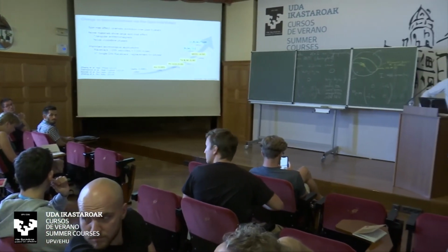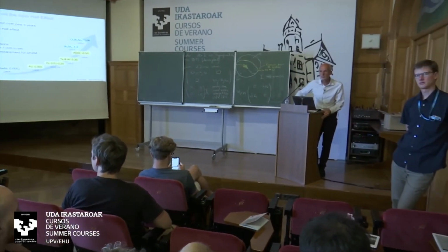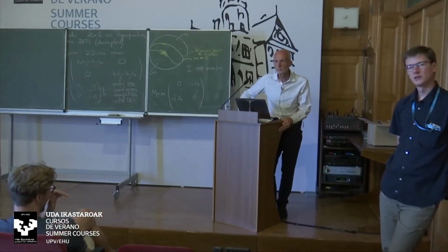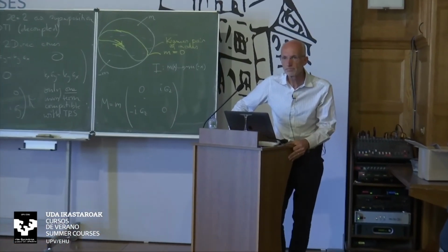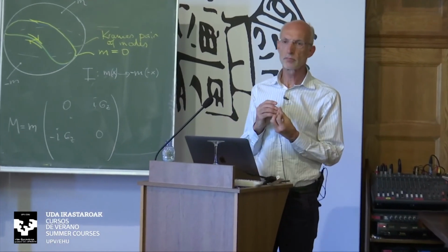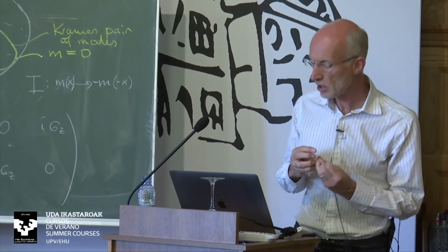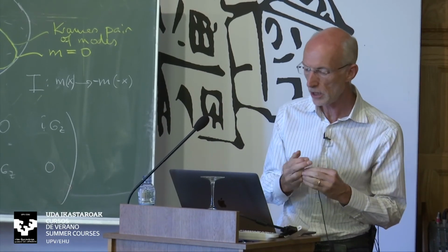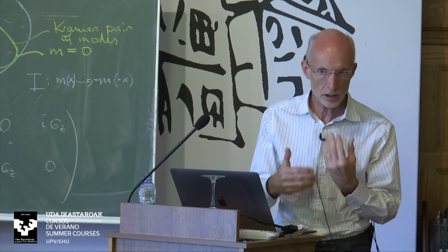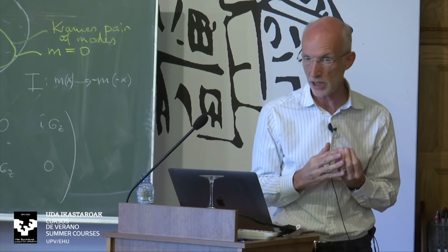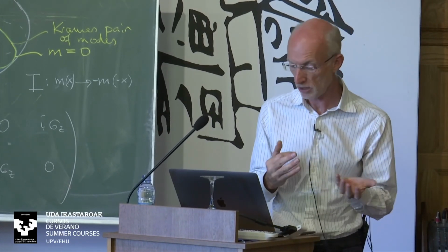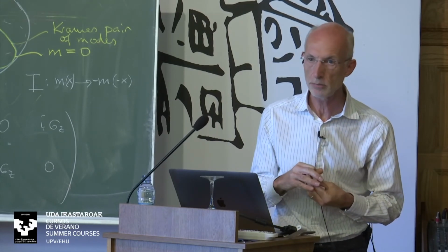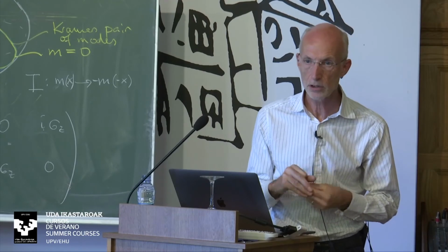I think your results are very interesting, but I'm wondering how you fabricate these devices. Do you make the rods with E-beam as well, or do you first prepare the rods and then do the contacts with E-beam? So it turns out that, even though these materials are based on layers that are just a few angstroms thick, we make them by conventional sputtering techniques, and we pattern the racetracks I showed you using just conventional optical and electron beam lithography. This is what was necessary.